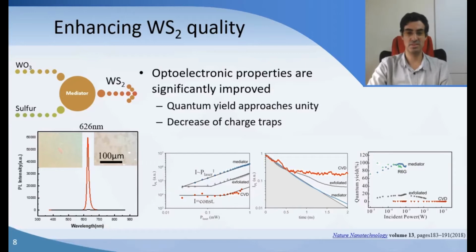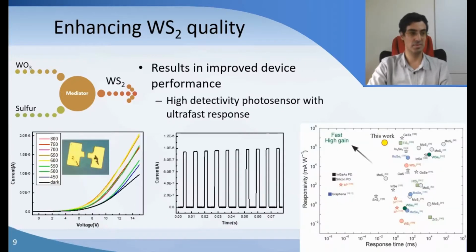We can translate that into electronic devices. Optoelectronic devices like photosensors are easy to do. They're just two-terminal. And we see that they're both very sensitive and very fast. The ultra-fast response is an easy way for us to check that the mobility is probably pretty high, and the responsivity tells us that we're not limited by traps, like by saturating traps. So that means that we can compete with existing materials in terms of quality. And so that's a promising direction.